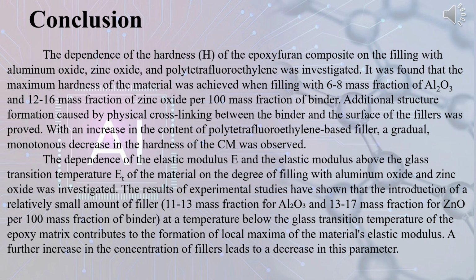So the conclusion is that it was found that the maximum hardness of the material was achieved when filling with 6 to 8 mass fractions of aluminum oxide and 12 to 16 mass fractions of zinc oxide per 100 mass fractions of binder. The results of experimental studies have shown that the introduction of a relatively small amount of filler at a temperature below the glass transition temperature of the epoxy matrix contributes to the formation of local maxima of the material's elastic modulus. A further increase in the concentration of fillers leads to a decrease in this parameter.